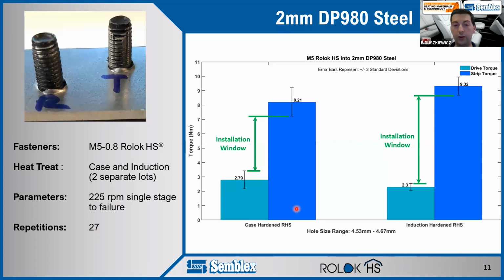But one of their questions was, do we do case hardened or do we do induction hardened? Obviously, case hardened is cheaper than induction, so if you can get away with case hardened, it certainly works well. So we ran both sets of data and left it up to our customer to decide. So if we look at the case hardened part, we see that we actually have a pretty good window for installation. Once again, we're on a hole size range, so the lower bar is our small hole size. The larger failure torque bar is our large hole size. And we've got a range anywhere from about 3.5 to 7 Newton meters with the case hardened part.